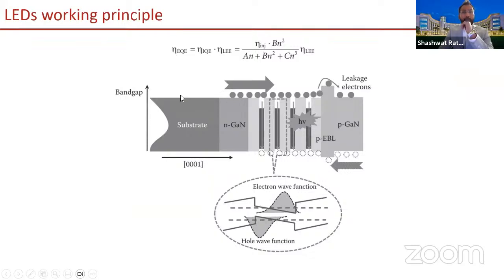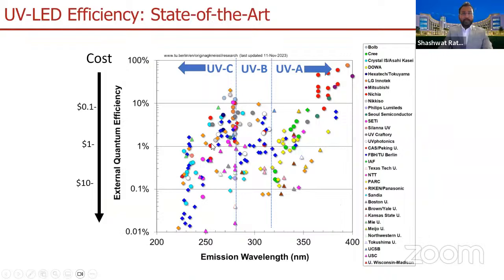So essentially, the way LEDs work is that you inject electrons from one end, and you inject holes from one end, and you make these electrons and holes overlap so that you generate a photon through this interaction. So this is how you generate light, but this process can be highly inefficient because of the challenges associated with these materials. And here I plot the experimental data that people have observed for external quantum efficiency as a function of emission wavelength.